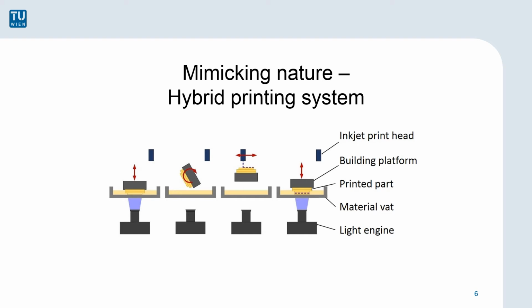In order to adapt the mechanical properties and improve the toughness of the brittle bulk material, we mimicked the structure of the spicules of the deep sea sponge. A hybrid printing system able to produce samples out of two different raw materials is used. This system consists of the aforementioned SLA process and an inkjet printing system. The SLA produces layers of strong and stiff material, while the inkjet system yields soft, compliant material layers.